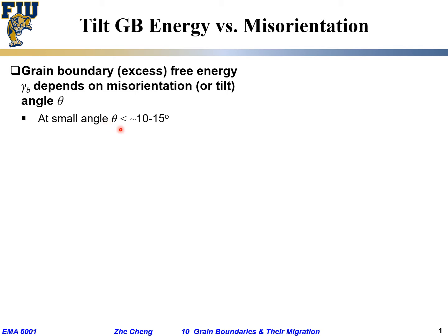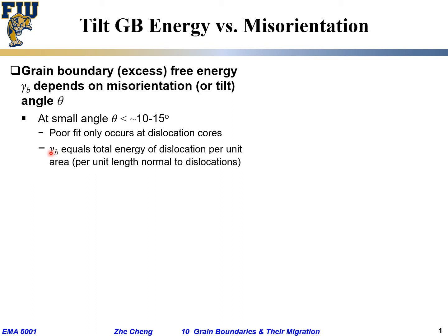When the tilt angle is very small — smaller than around 10 to 15 degrees — almost all of the misfit of atoms is only occurring at the dislocation core, at the center of that linear one-dimensional defect which we call a dislocation. Then gamma_b, the interfacial energy — in this case grain boundary energy — would be the summation of the total energy from the array of dislocations per unit area.